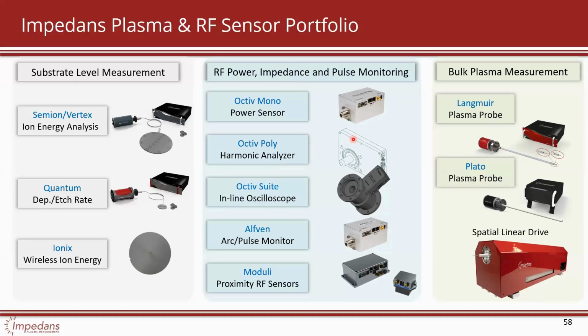It was curving back on itself and looked really strange. But if you look at the amount of current the Langmuir probe was drawing, it was approaching the current that was going into the plasma. So you're completely sucking out all the ions. Just keep that in mind, so there is a dependency. I'll give one hint here.